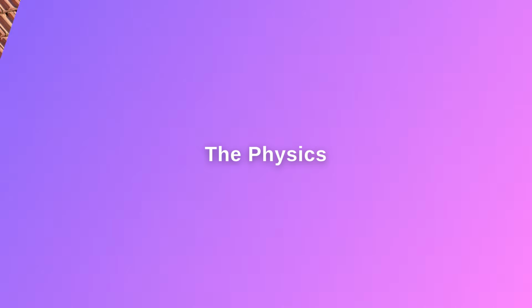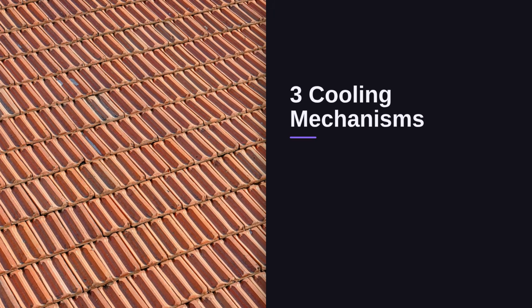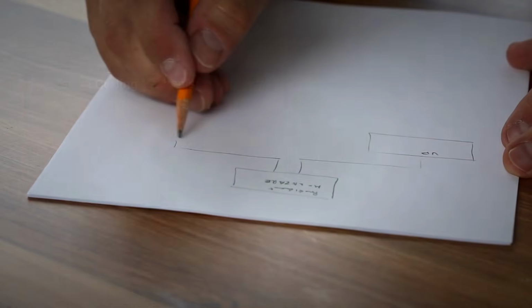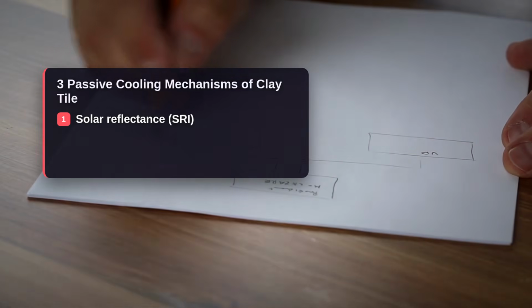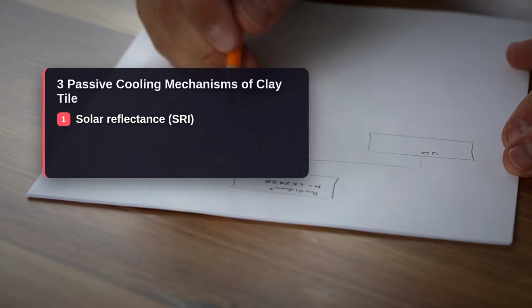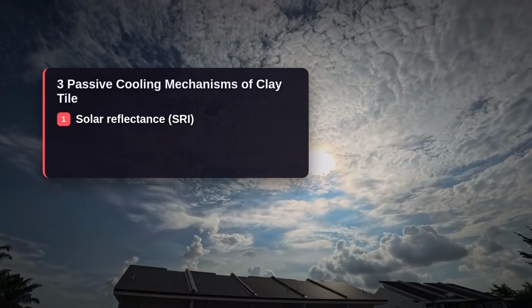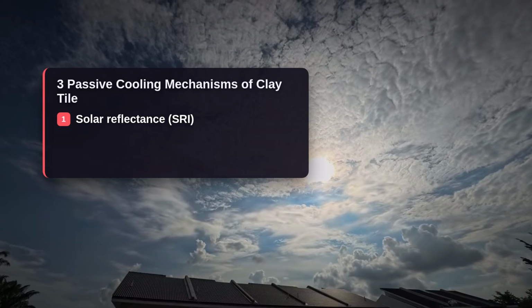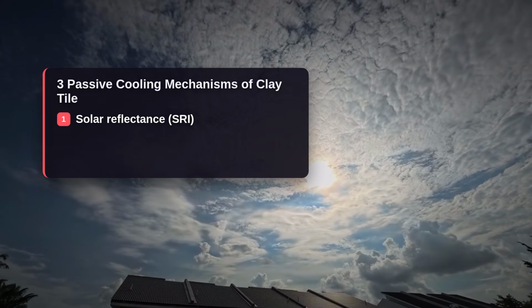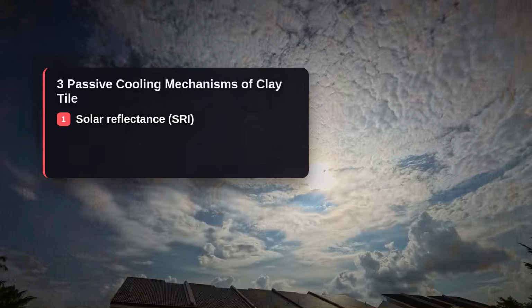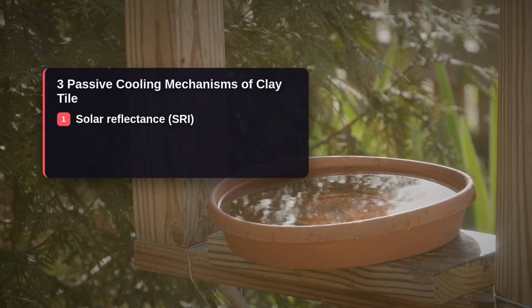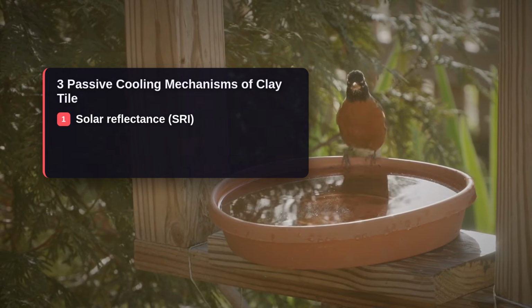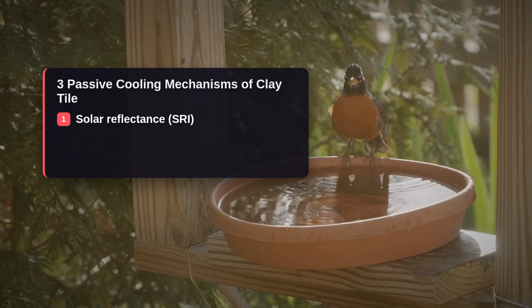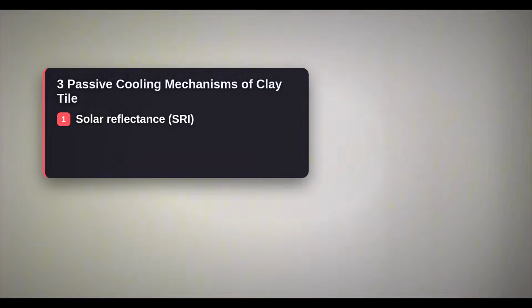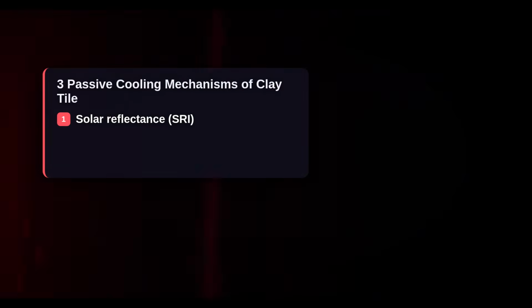Now let's talk about what clay tile does instead, and why it does it through three separate mechanisms that compound each other. The first mechanism is solar reflectance. Natural terracotta clay tile, depending on its color and surface finish, has an SRI between 40 and 70. Lighter glazed tiles can reach SRI values above 80. Compare that to asphalt at 4 to 22. More of the solar energy bounces back into the sky before it ever becomes heat in your roof system. That is the most straightforward gain, and it alone can reduce peak surface temperatures by 40 to 50 degrees Fahrenheit.